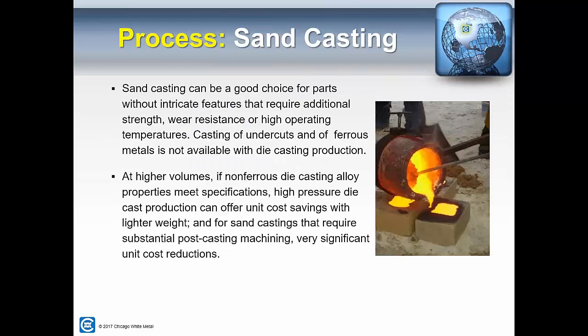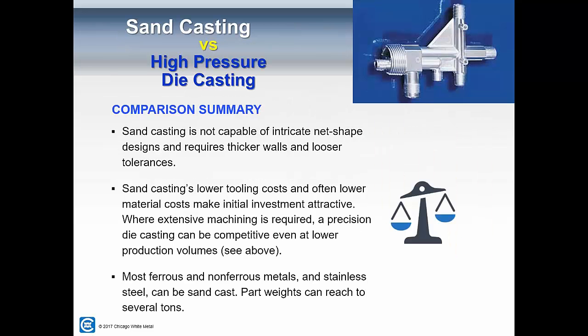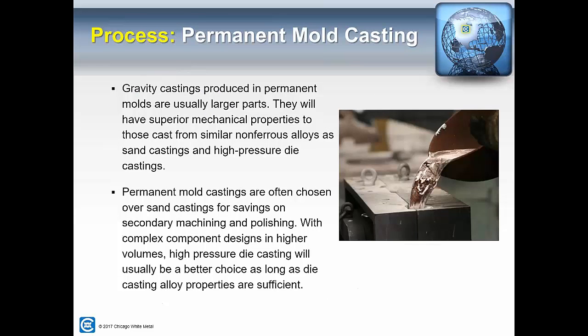Sand casting is a very good choice for low volume applications without a lot of detailed features, because die casting can cast thinner walls than sand and much more complex shapes, and so that's why it generally breaks down. You use sand casting, maybe add some machining to it if the volume is low, and you move to die casting as the volume increases. The typical die casting part on the right shows the complexity, including cast-in threads on the OD, which are possible to do with die casting.